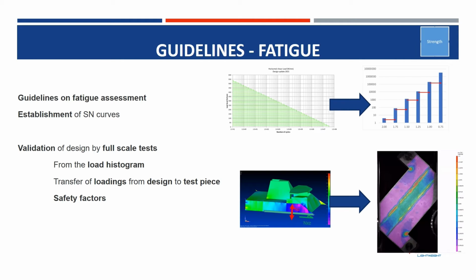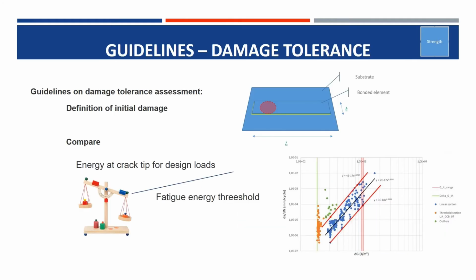Next step is the guideline for the fatigue assessment. So there are guidelines for the establishment of SN curves, but also for the validation of design by full-scale test. This is from the load histogram to the transfer, and the load histogram to the test piece, and also the associated safety factor. For the damage tolerance, there's an assessment of damage tolerance which is guided, mainly on the definition of the initial damage, which is a very important parameter in such analysis, which will depend on the inspection protocol, etc. Then we can compare the energy at the crack tip for the design load to the fatigue energy threshold that can be, as it was done in Qualify, experimentally determined.